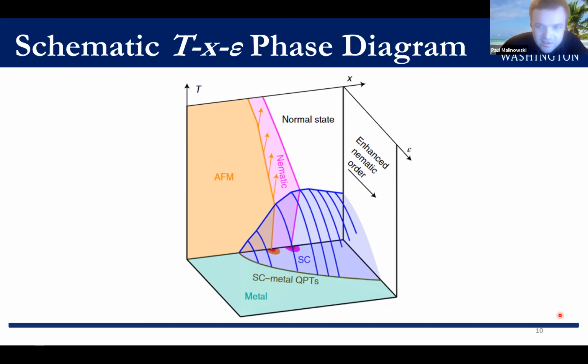Now, these findings are interesting for a few different reasons. So one, in the case where superconductivity can be completely destroyed, this provides a platform for studying a superconductor to metal quantum phase transition in a bulk 3D system with strain as a clean in situ tuning parameter. And two, it's a direct demonstration of the importance of the fluctuations of the competing nematic and magnetic phases, because in the same sample, we can use strain to strengthen or weaken those fluctuations and see how the superconducting state